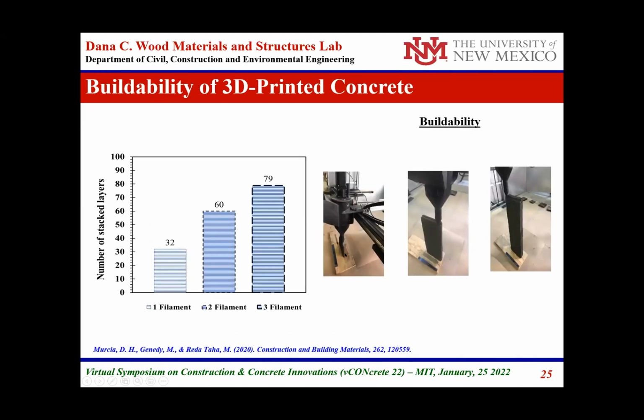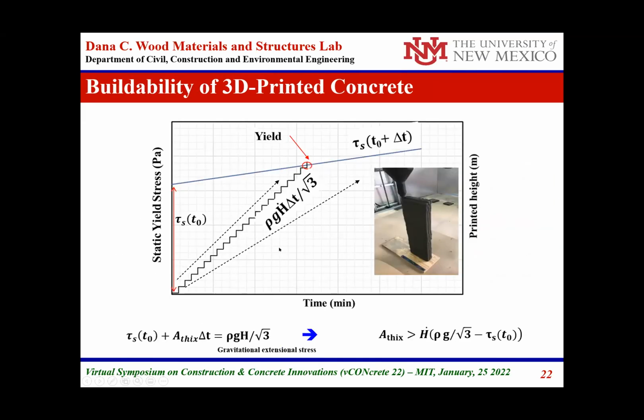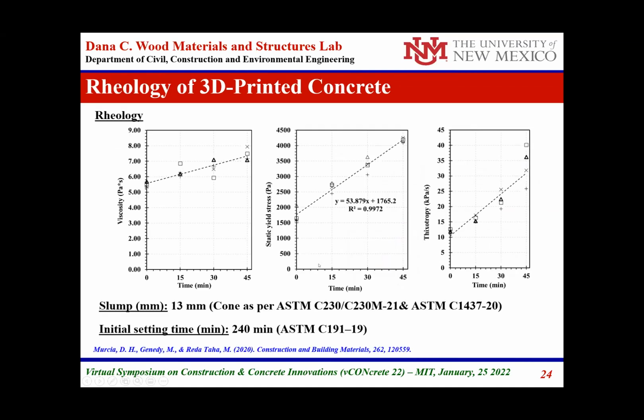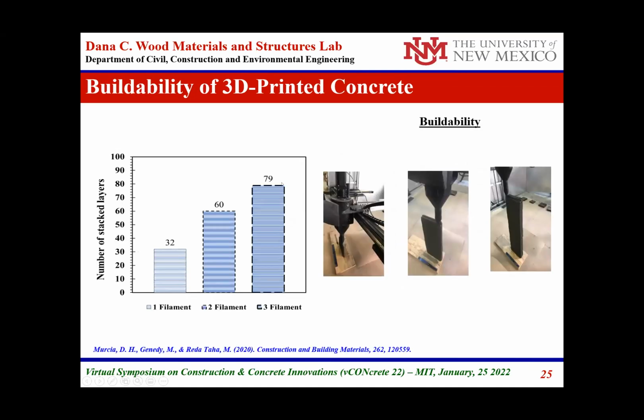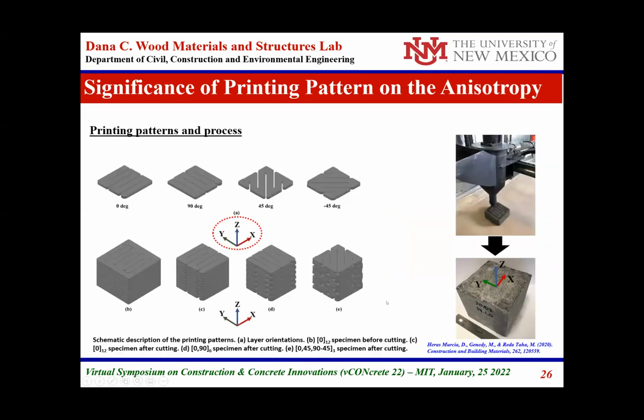We also measured the buildability by building or printing one, two, and three filaments. One important thing I missed to mention is that this only represents the strength of the material, not the structural stability and the tendency for buckling, which we're going to talk about later. So the filament strength here is being measured to quantify the ability of the material to allow buildability. As you can see, as the number of filaments increases, the number of stacked layers can increase, and that is in the concrete mix we choose.